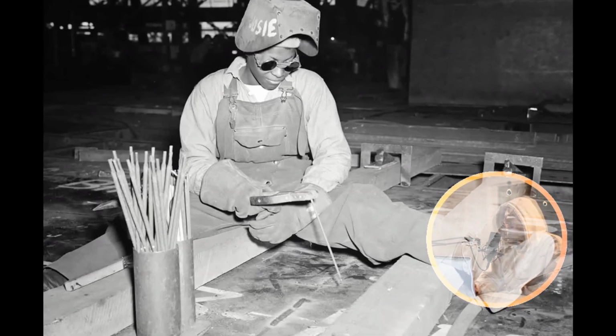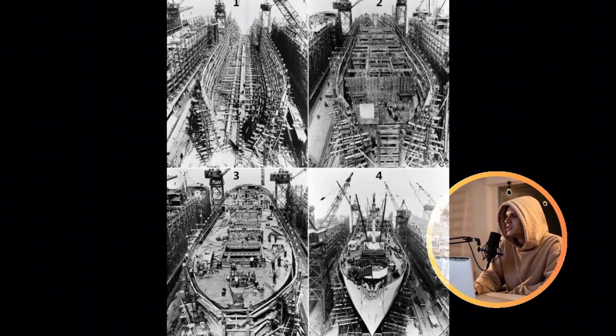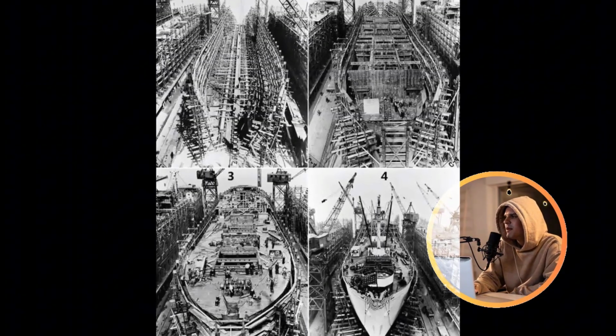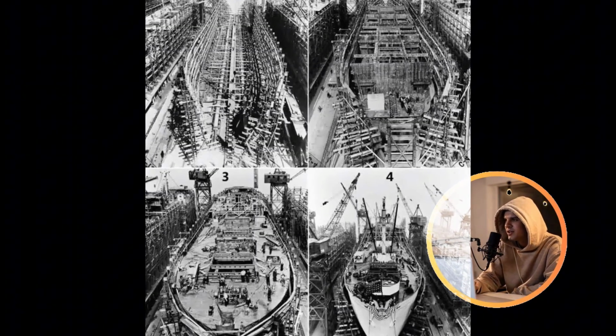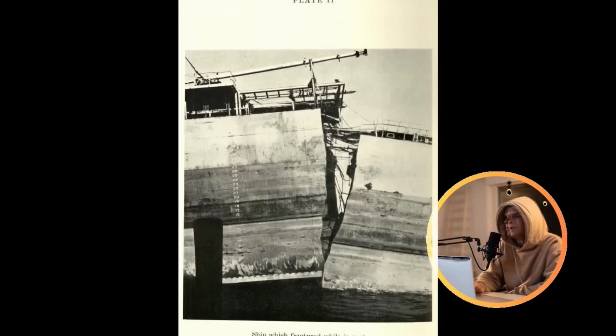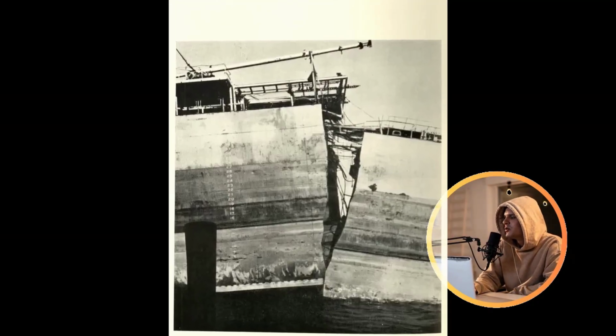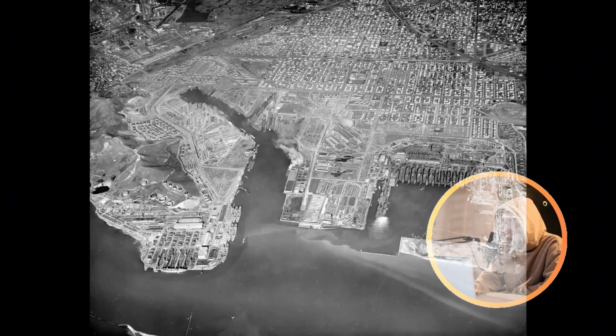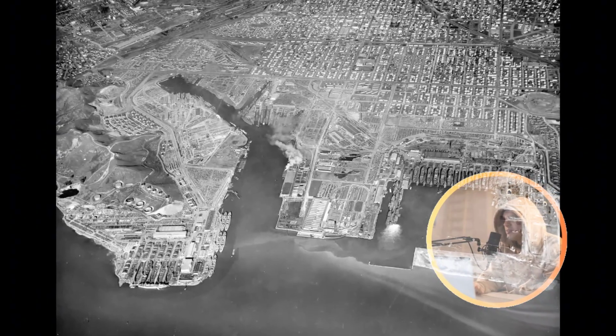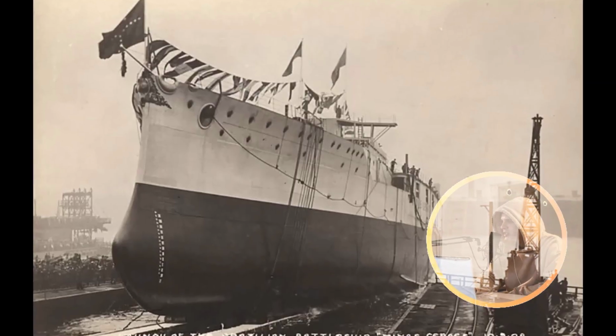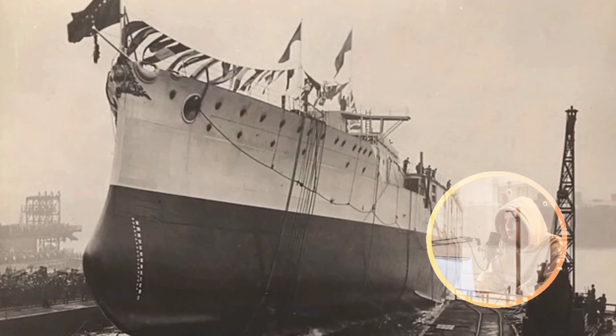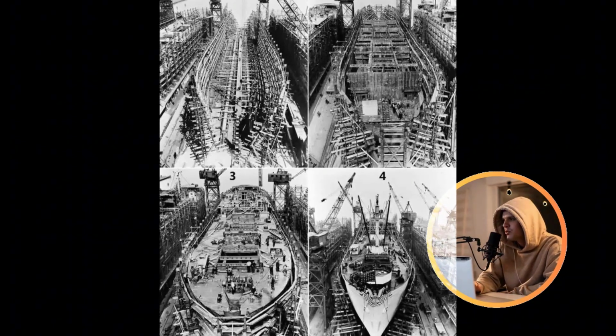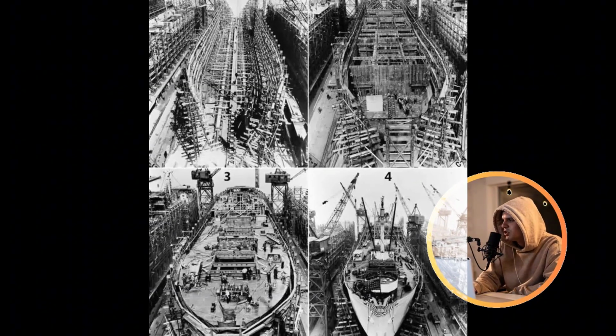The catastrophic failure of the SS Schenectady, while shocking at the time, became entirely comprehensible upon closer examination. Constructed during the bitter cold of early winter, its structural integrity was compromised by welding sequences that inadvertently maximized internal stresses, leaving its hull burdened with tens of millions of pounds of latent tension. When the Portland morning temperature plummeted to a frigid 28 degrees Fahrenheit, the steel, already under immense duress, became dangerously brittle. A critical stress concentration, located precisely at a hatch corner, served as the initiation point for a devastating crack.